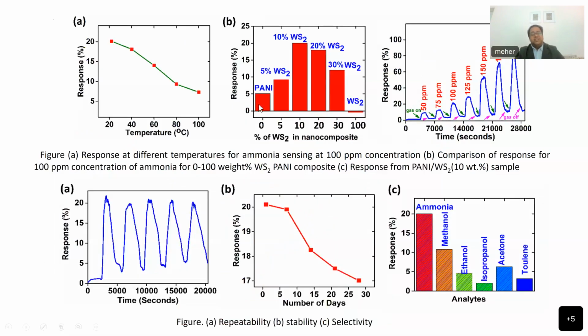If you see here, the interesting thing is polyaniline is not a very good sensor for ammonia. Tungsten sulfide is not at all a sensor for ammonia. But if we make a composite of it, it is sensing nicely. So at around 10%, we optimized the process so that the sensing is the highest. And we have checked it with different ppms also. So we increase the ppm level in steps and see that our sensor could sense the gas.